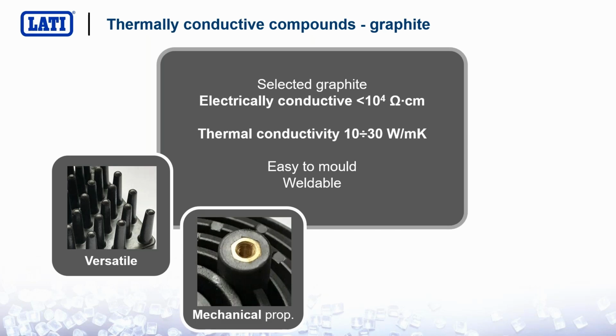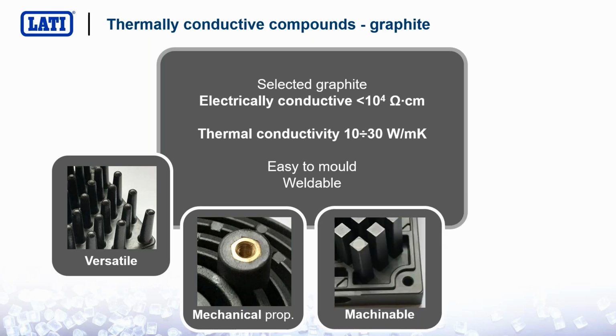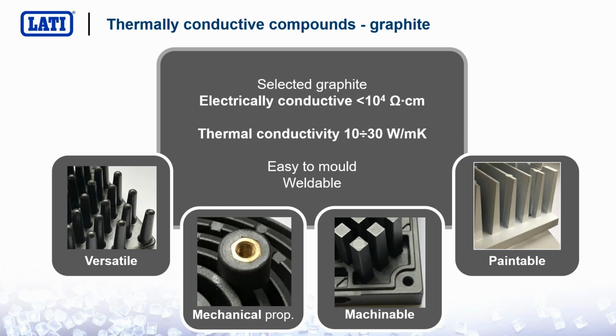They can accept inserts and they can be machined. So from a mechanical point of view, they're very interesting compounds. You can somehow drill holes. You can use screws directly into these graphite-based thermally conductive plastics, on the contrary of ceramic-based, which are more brittle. And then you can also paint them because of being electrically conductive. You can somehow use the modern powder painting techniques.